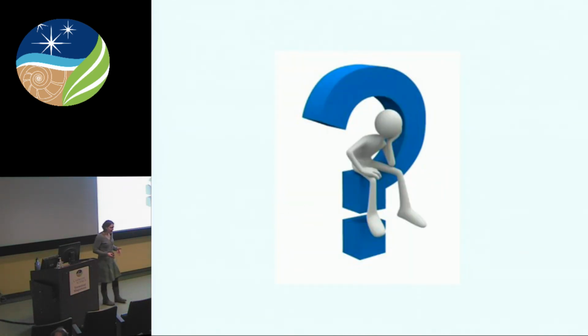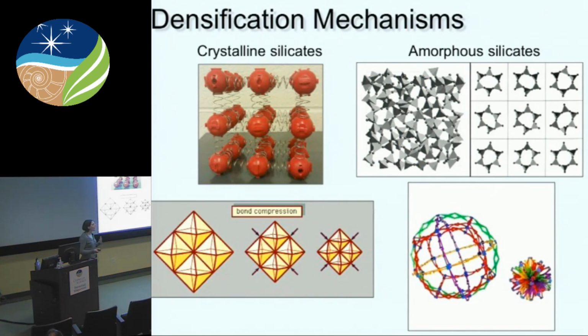So at this point, I have to start asking myself, if every behavior is anomalous, maybe we're not describing the behavior very well at all. Maybe we need a new way to describe the behavior of these materials at high pressure and temperature. For that, I've borrowed a lot from the work in materials science and Martin Dove's group. They have proposed that in amorphous silicates there's a property termed network flexibility. If we think about crystalline silicates, as I talked about earlier, you have atoms that are bonded together, and we're basically compressing the interatomic potentials, shortening the bond distances as we compress them, so we get a stiffer and stiffer response as we reduce volume.